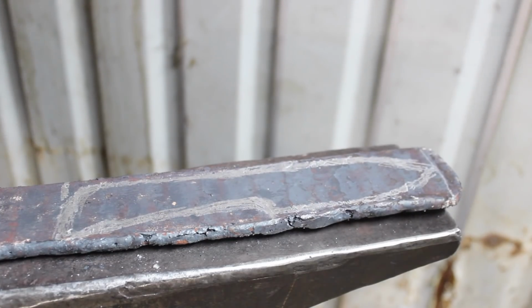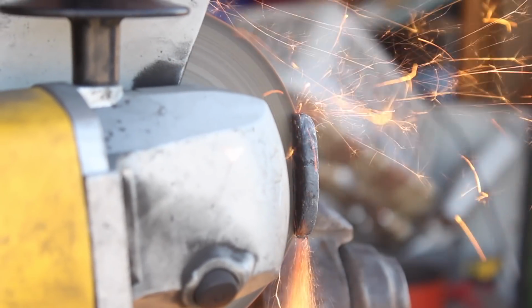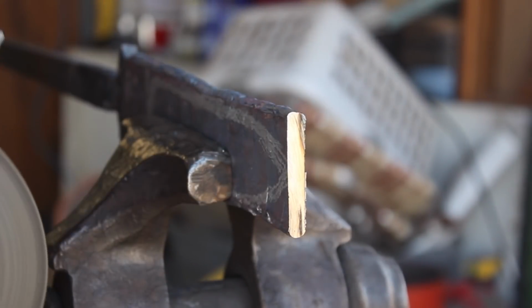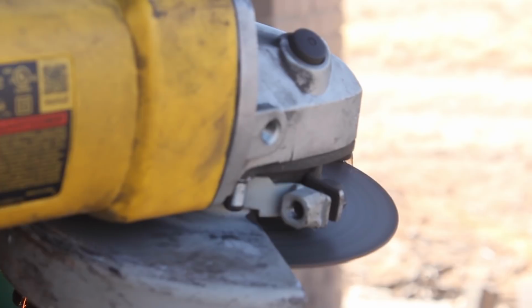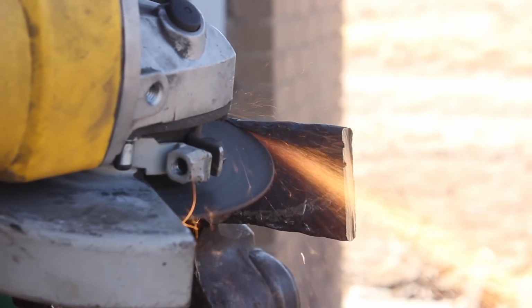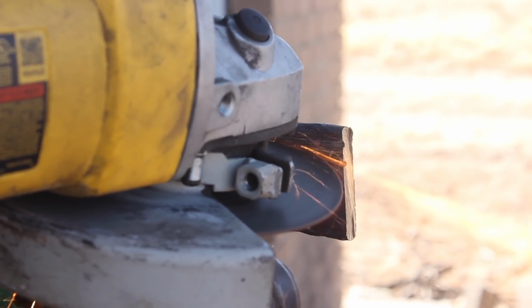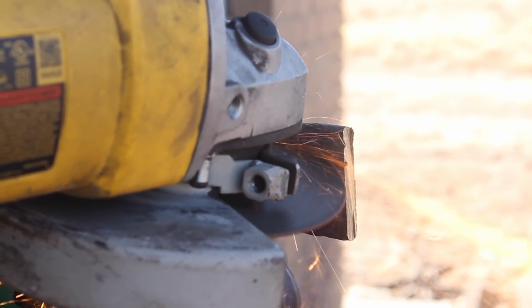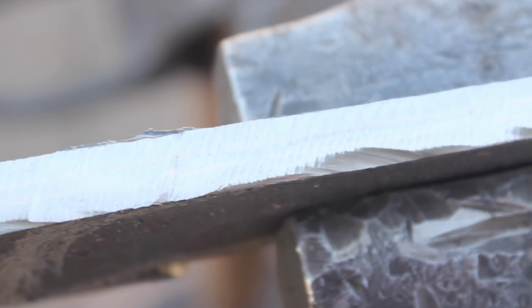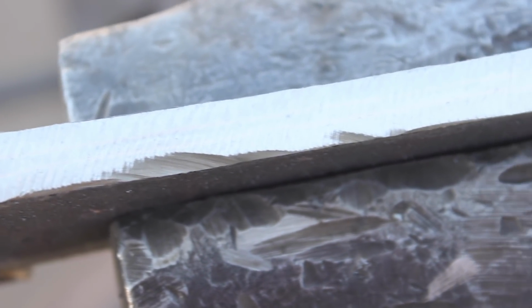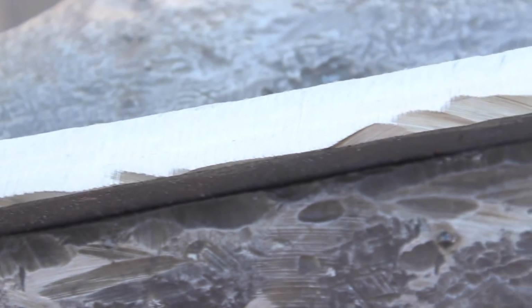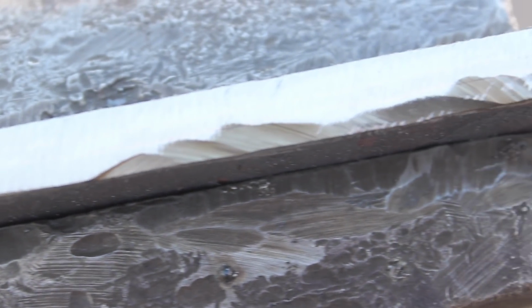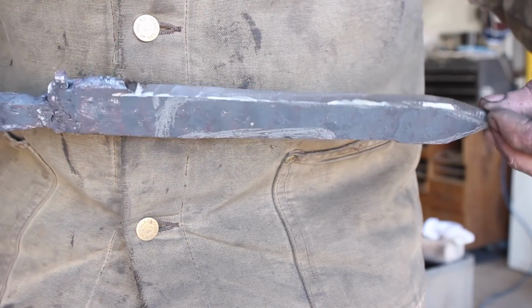So this is take 2. Rebuild the whole billet, repeated all the operations that you just saw, and it appears we have a decent billet. I kept things cleaner and had more material here because I did forge out my Damascus, or pattern welded, to the appropriate width as well as the copper sheeting. So a lot cleaner all the way around.